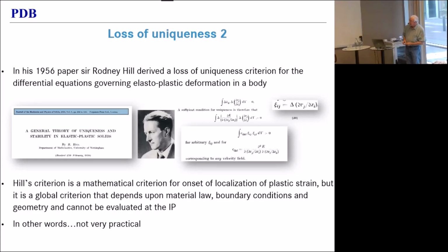Well, if you have a very nasty, difficult question, you can always ask Sir Rodney Hill, or at least you could, as long as he was alive. And if you go back to the literature, in 1956, he published a paper which actually gives a mathematical criterion for the onset of localization of plastic strain, which he identified with the loss of uniqueness of the mechanical problem. But if you look at the formulas there's an integral. And that integral goes over the entire domain. So it's a global criterion that depends on the material law, on the boundary conditions, and on the geometry of your structure. It's not something that you can evaluate at the level of the integration point. So for implementation in a code, it's maybe not very practical.